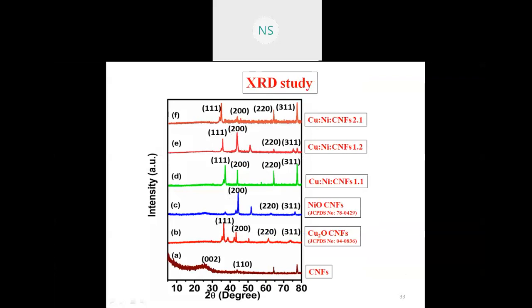So this is the XRD study of this particular copper nickel carbon nanofiber ratio. Initially we have the nanoparticles we synthesized: copper oxide carbon nanofiber, nickel oxide carbon nanofiber, then copper nickel carbon nanofiber of 1:1, copper nickel carbon nanofiber 1:2, copper nickel carbon nanofiber 2:1. And if you look, a uniform pattern can be obtained in every ratio, that is 1:1, 1:2, and 2:1.